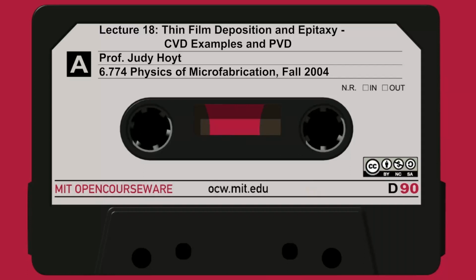So again, going back to slide 18, I have a formula here that you can use to calculate the evaporation rate, depending on this vapor pressure, P sub E, at the evaporation temperature. So the evaporation rate is naturally proportional to vapor pressure at the evaporation temperature. Depending on the element, whether you're trying to evaporate indium, well, indium you can do at pretty low temperatures. Look at its vapor pressure. It skyrockets above about 550 centigrade.